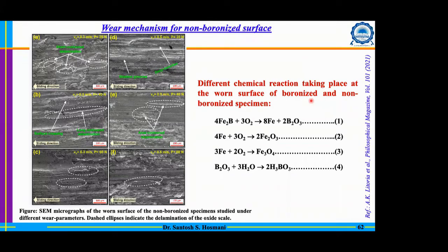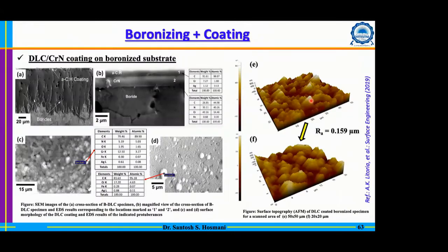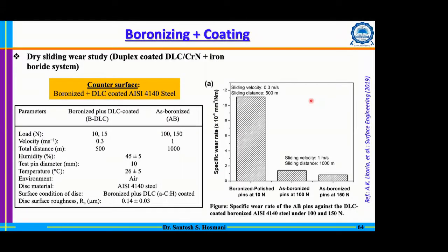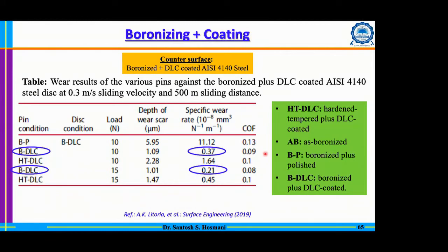Now the DLC coating I will just show here. So either of the surfaces is DLC coated, that means the counter surface and/or the boronized surface. In that case, your wear performance is extremely good. Even at a high load such as 100 Newton or 150 Newton, it performs very well. Because of the DLC coating, your coefficient of friction is also very, very low compared to that of your earlier. You can see the value is 0.09 or even close to 0.1. It's an extremely good value you can get by using the DLC coating.